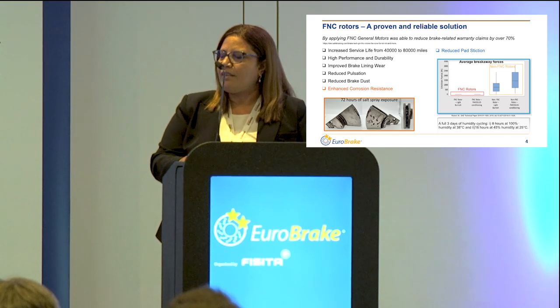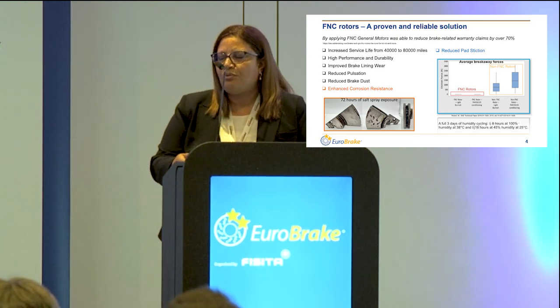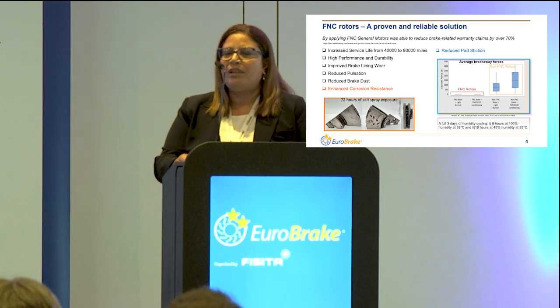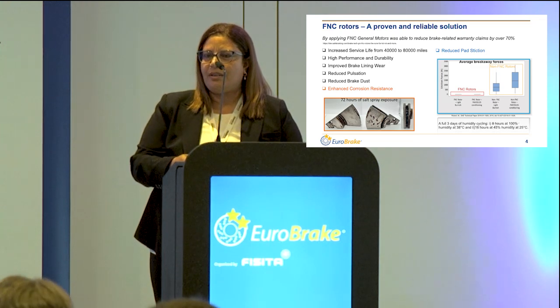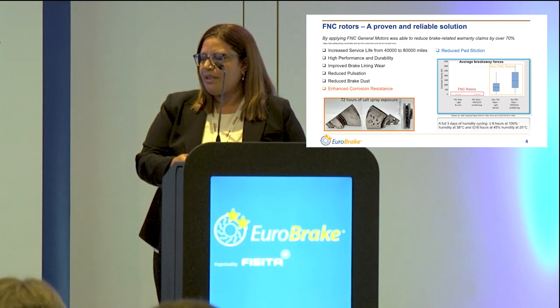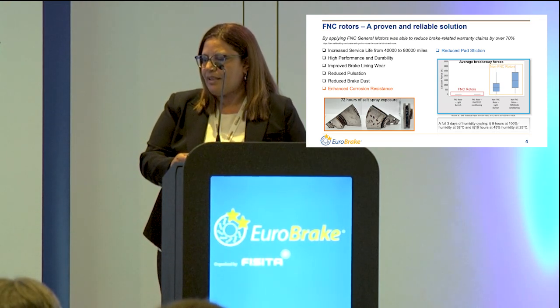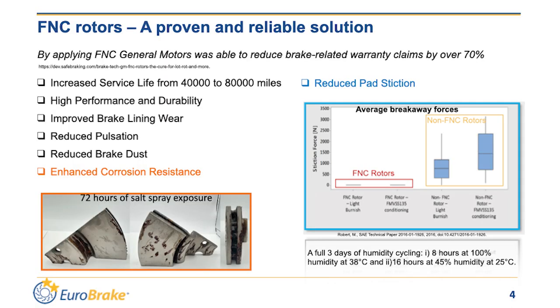And they enhanced the corrosion resistance, but I should note that using only ferritic nitrocarburizing will give just a slight improvement, as demonstrated here in this picture for an FNC treated sample. After 72 hours, there is a lot of rust that forms.